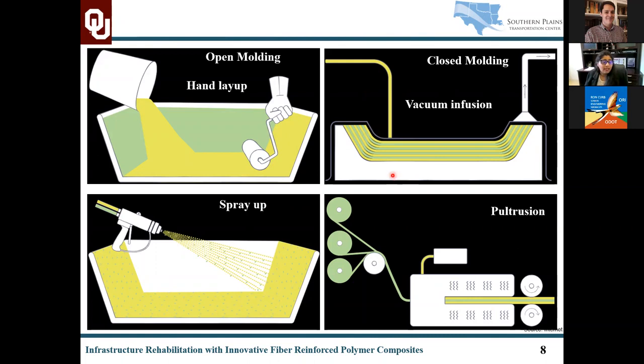Hand layup can also be accommodated with vacuum infusion, where any additional resin is eliminated from the process, and it ensures higher strength and higher consistency in the process of manufacturing. The spray up technique ensures that as much resin as needed is used for impregnating the fiber sheets, fiber textiles and fabrics for the sheet formations. And pultrusion is primarily used for bars and sections, with different kinds of rovings that are impregnated into the resin, followed by the curing and heating process with a die.